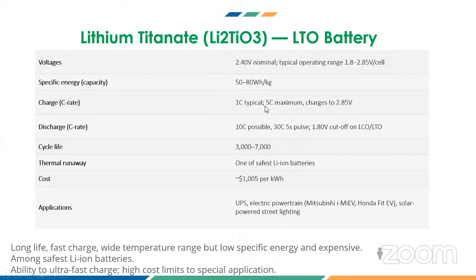And the charging time also can be reduced by above 5 times, and the discharge rate also up to 30 C is possible. So that means rapid charging as well as discharging is possible in the case of lithium titanate. But the major drawback is specific energy is less. Specific energy capacity is less means we need more number of batteries or more weight. The weight of the vehicle will be increased. So this is one of the drawbacks.